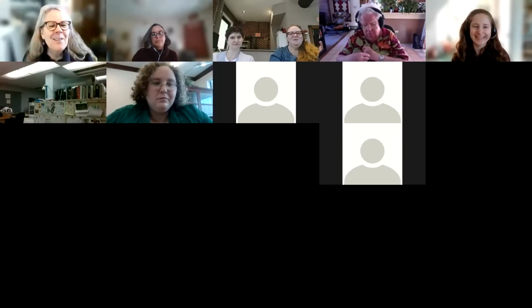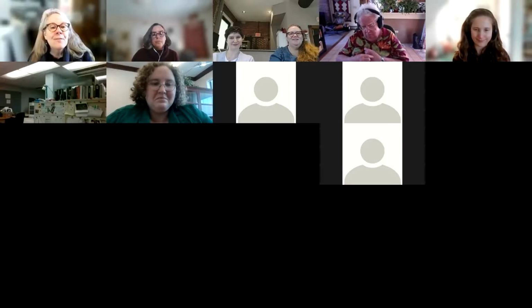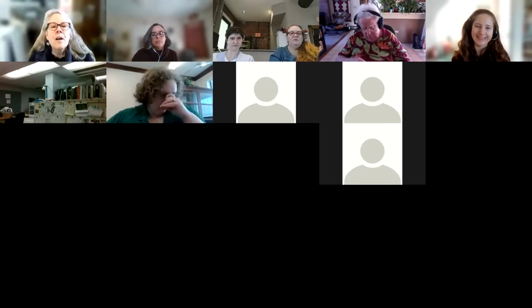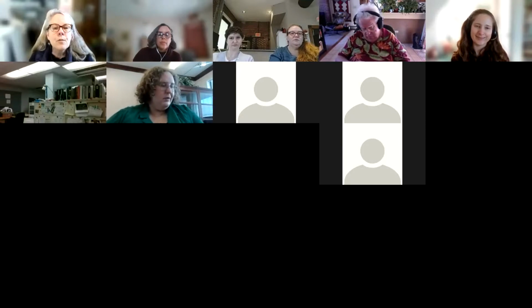Right. I'm glad you asked that. You can never ask too many safety questions, because there are a lot of hazards in the museum. Everyone thinks the museum is such a tranquil place to work, but there's a lot of hazards out there. So no, I think it's really cellulose nitrate film, which is the oldest type of film that is explosive. If you do have old film canisters and you can tell that they're heavy, that there's something in there, I would open them outside. You might have a loading dock, some place outside where you could open them. I would wear safety glasses, goggles. I would do it with another person, so you're not by yourself, a buddy system, because this can be tricky.